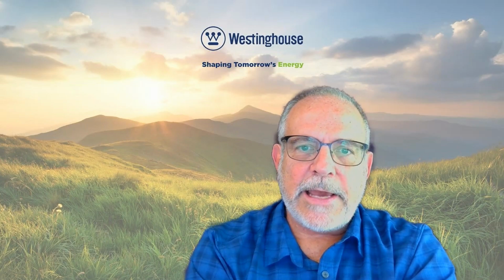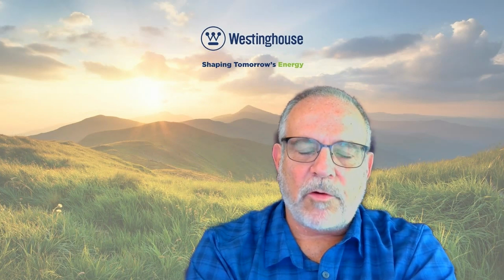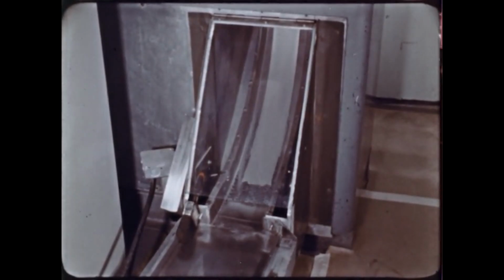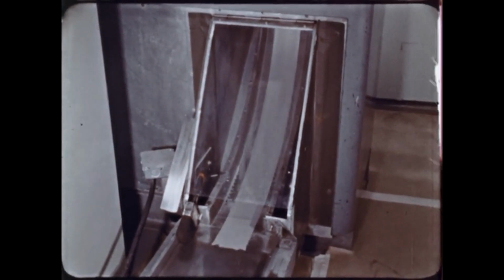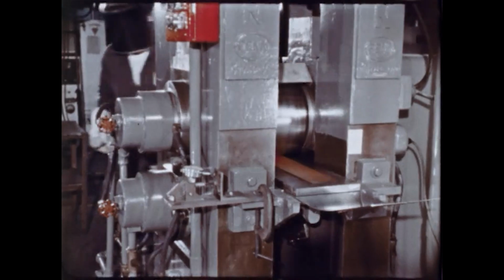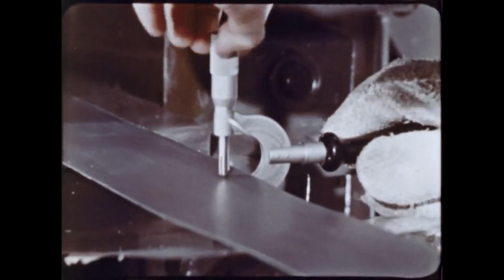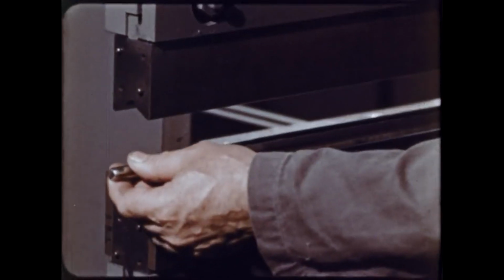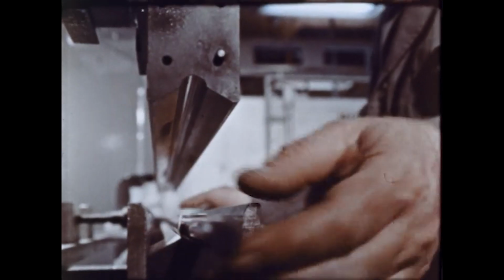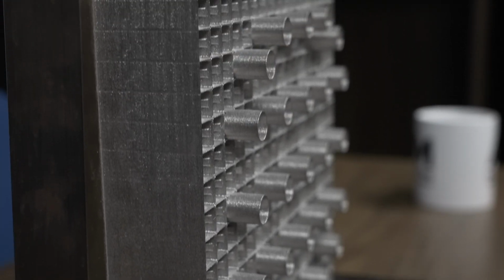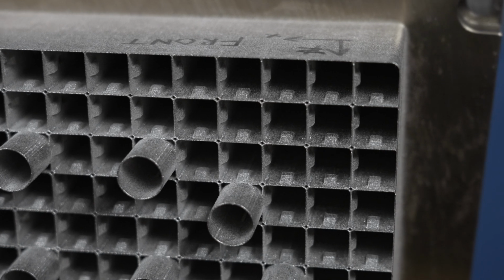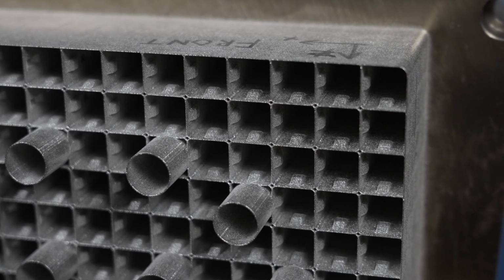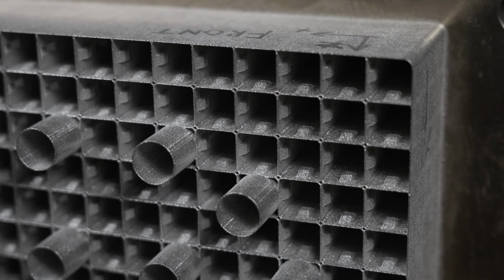Where the fuel rods contact the spacer grids, if that surface is too rough, then it could wear breaches in the cladding that contain the fissile material inside of the fuel rod, thus leaking that material into the coolant. Which creates a lot of expense and extended outage times. Part of the project actually looked at trying to reduce that surface roughness, which we were at least partially successful in. As it stands today, they're still a little bit too rough, and so we've been using electromechanical polishing to treat those surface areas that are in contact with the fuel rods.